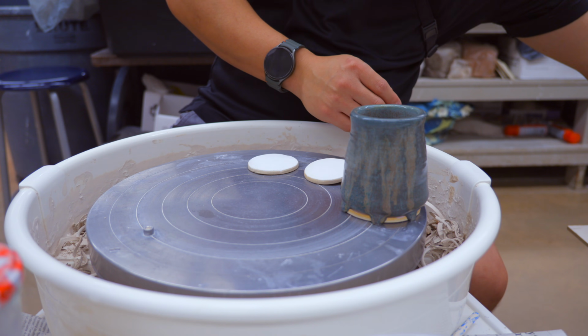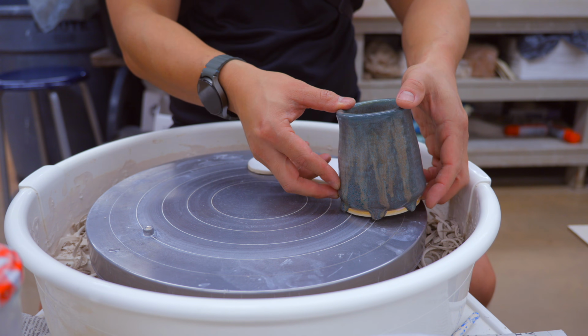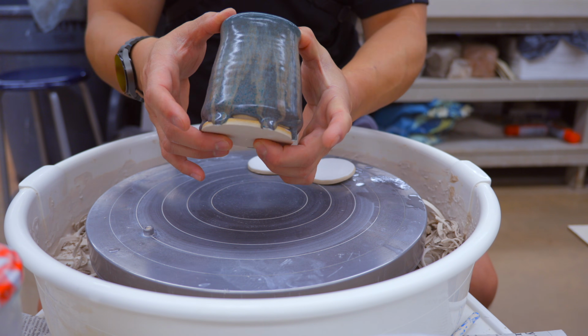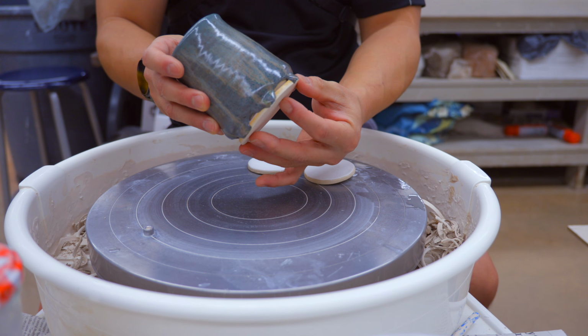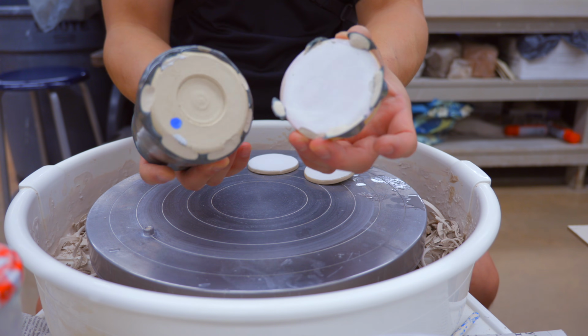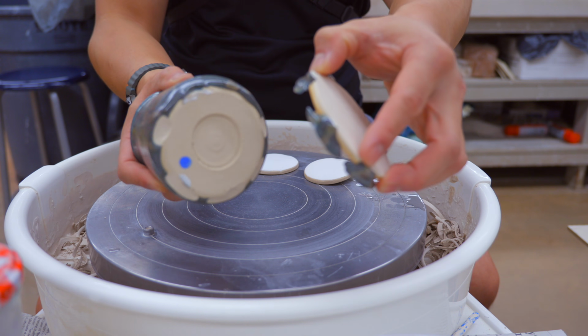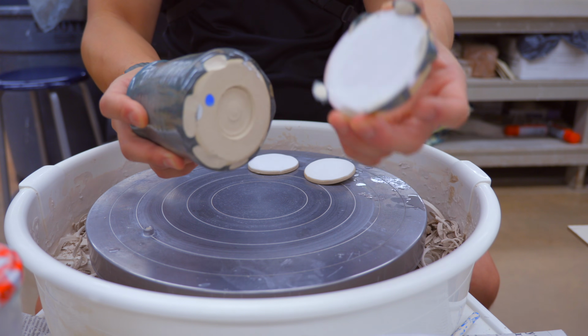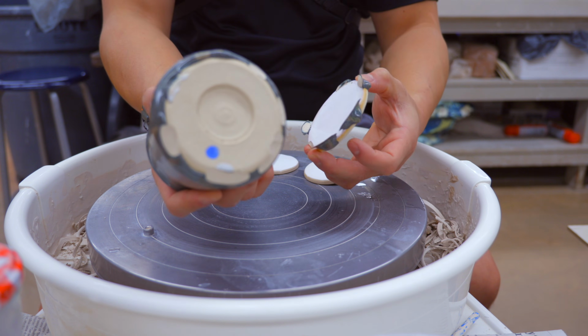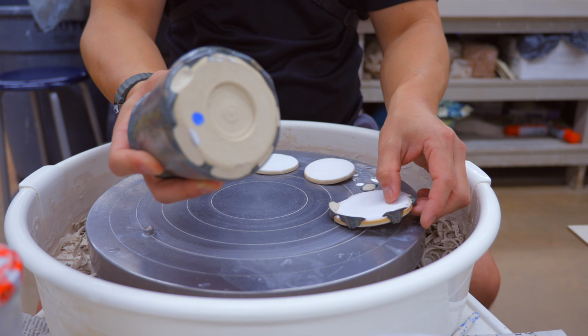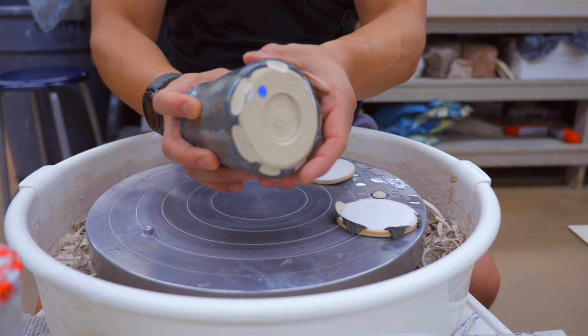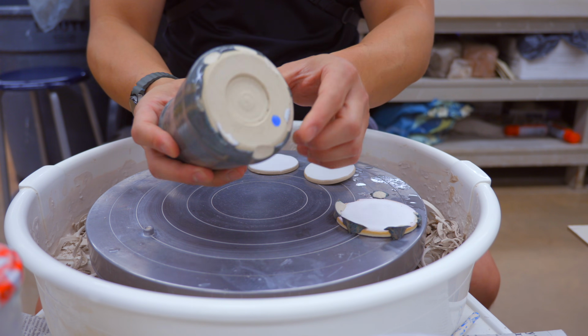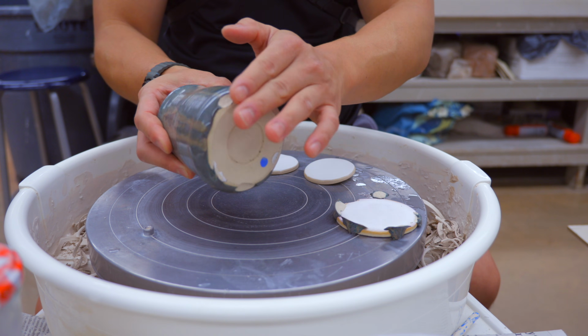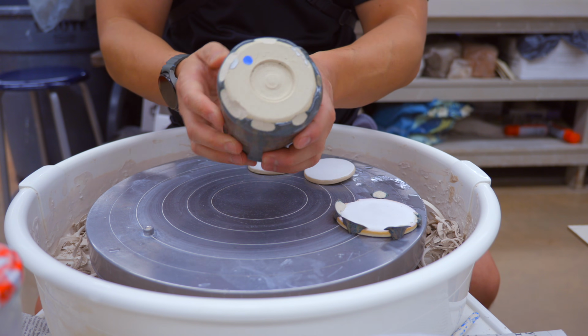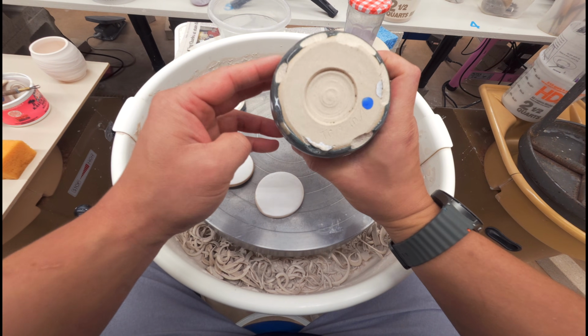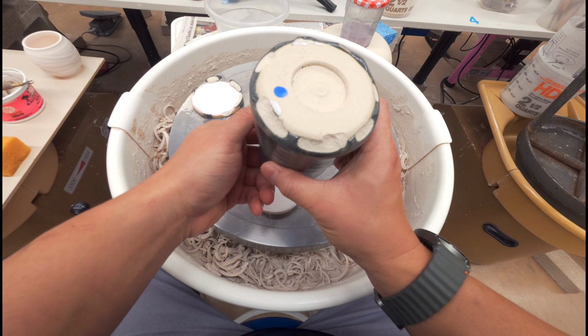And so what happens, here's another example of a beautiful glaze piece, but just too much. So if you can release the cookie, you pop it off, and what usually happens is glaze and part of the clay gets removed and stuck to the cookie. And then what you're left with is just a really sharp piece. Now this is all glass on here. This is glass that can cut your finger. So you gotta be very careful when you touch this. You'd have to sand or grind this smooth if you wanna use this. So usually most pieces you have to scrap, but there is a way to fix it, and I can kind of go over that later.